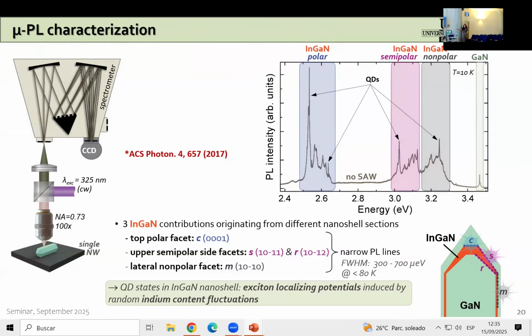We also observed, as you can see here, the presence of such intense and sharp emission lines, which are superimposed on the overall emission band. We can observe some of these lines up to some 80 Kelvin. At low temperature, they have a linewidth of about 300 to 700 microelectronvolts, which is not so bad. We basically attribute the presence of these lines to exciton localizing potentials, which are induced by random fluctuation of indium content across this InGaN nanoshell. So basically, there is a clustering of indium inside the indium gallium nitride nanoshell, and this clustering acts as a quantum dot confinement potential, which is optically active and is able to emit single photons.